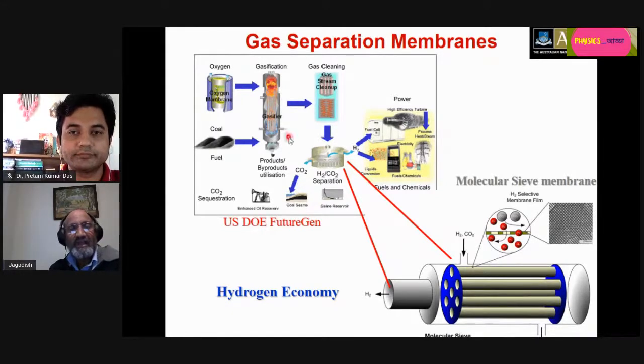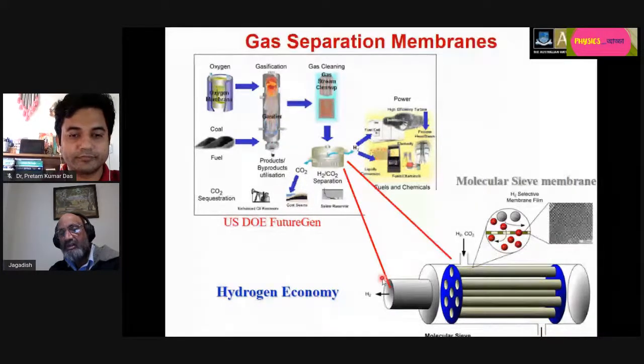So meanwhile, can we really convert coal into gas, gasify it? Because these are hydrocarbons, essentially what you got here. And then you bring the coal and oxygen, and essentially it creates a gas byproduct. And then you'll be able to separate the hydrogen and carbon dioxide. So essentially these membranes have got holes such that only the hydrogen molecules can penetrate through. Carbon dioxide molecules are too big to penetrate through. So that means you bring in this mixture here, hydrogen comes out here, and the carbon dioxide comes out here because it cannot go through the membrane. That means you're able to separate these things.